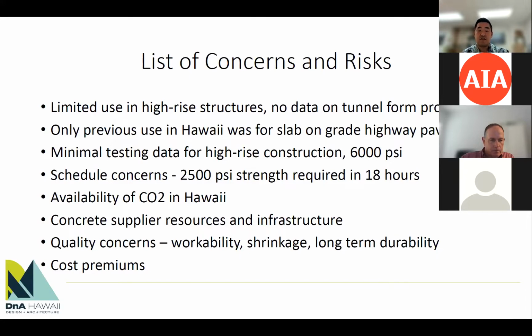Previously, like I mentioned, the only use in Hawaii was for slab on grade work, which is much lower risk than elevated, suspended slabs and walls. Along with that, the testing data for Carboncure injections was limited for the concrete we were looking for. We were looking for a 6,000 psi concrete mix. Most of the applications we found were 4,000 or 5,000, which is more common in buildings.